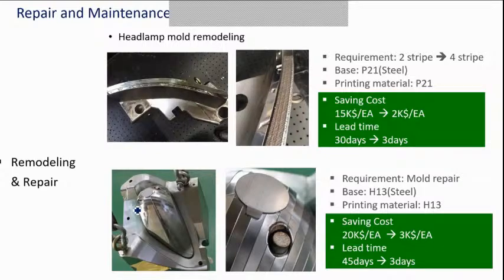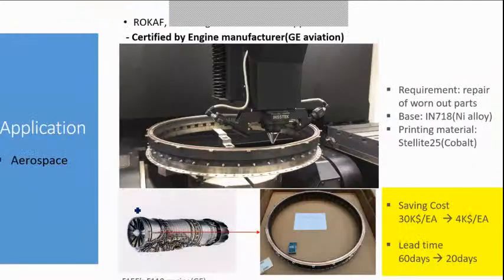And this fusion is perfect. When you take an X-ray, you are able to see that the fusion has happened between the old part and the new part, unlike welding, where the welding lines get seen. And this can be used for repair. One of the cases in Korea is that an engine workshop could use it directly to repair the front portion, which is called the shroud, and which gets hit by birds, using 3D printing.